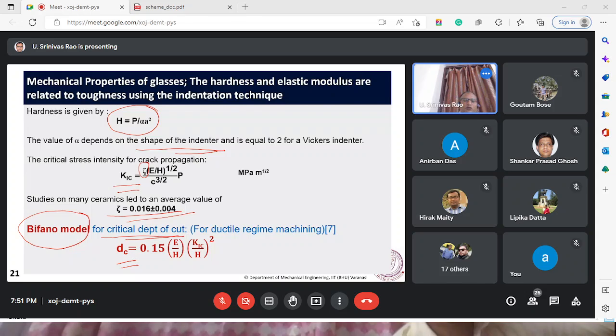From this actually there is a calculation for model developed for this critical depth of cut, which is related in terms of elasticity of the material, hardness of the material, and fracture toughness of the material. So through elasticity, that is Young's elastic modulus, hardness, fracture toughness, these are all material properties. Through these material properties, we can arrive at the critical depth of cut. Now, this critical depth of cut is a very small value.